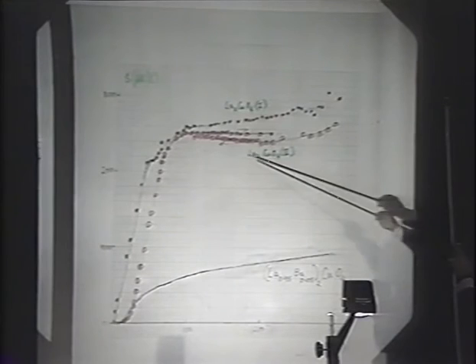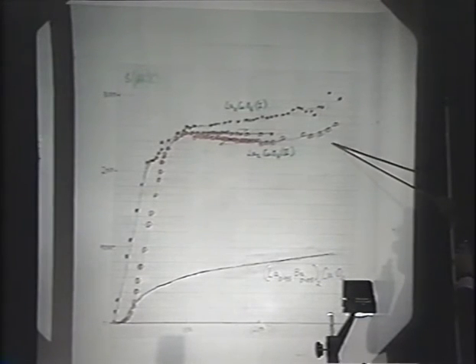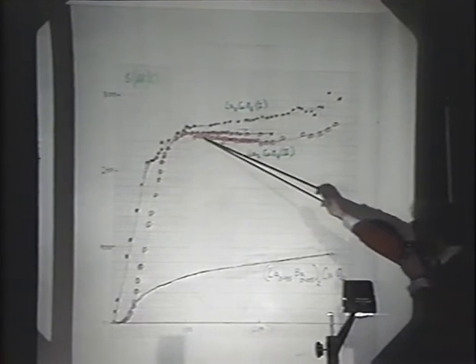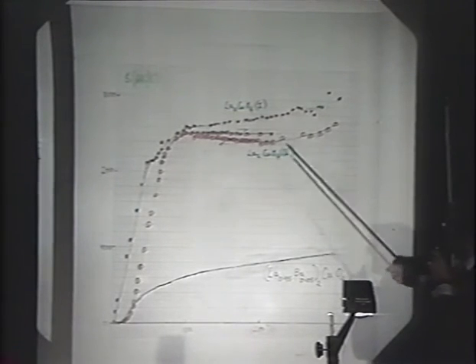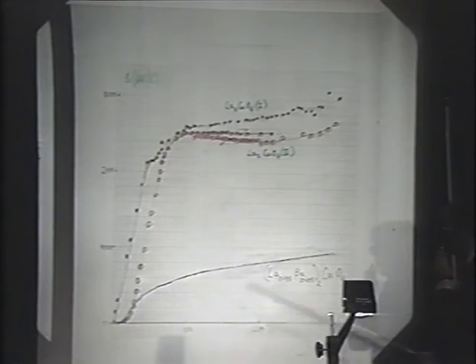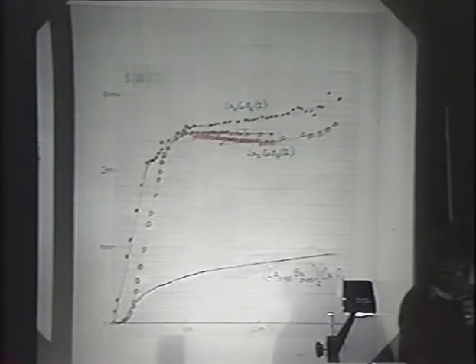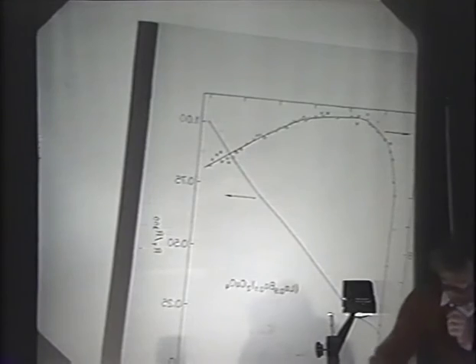So this shows some experimental results on what we call the pure stuff. This is 2 independent preparations of lanthanum copper oxide. And you can see that the main thing is a temperature-independent large positive thermal power, indications of superconductivity, perhaps from the surface at high temperatures, 80 K, then falling nearly to 0. And then with very small amounts of barium, the thermal power really shoots down. I'll just show one curve.